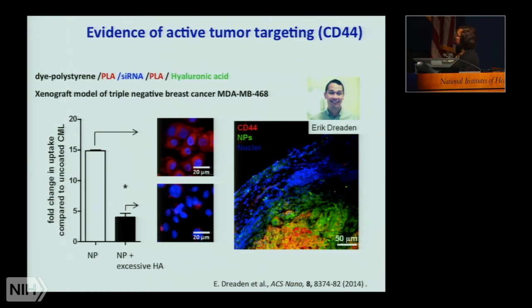In this work, we looked at xenografts of triple-negative breast cancer, and we did show that these overexpress CD44. When we look at the uptake of these nanoparticles labeled red in this image here, we see a huge amount of uptake, about 15 times that of a layer-by-layer particle that contains dextran sulfate, similar charge, no hyaluronic acid. And we can also titrate out the interaction by adding excess hyaluronic acid, and here you can see that almost completely eliminates the uptake.